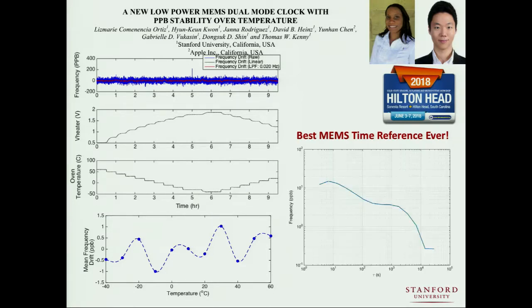It's very repeatable. If you make an Allan deviation out of the data on the upper left, there's details here that have to do with what's going on in the environment. I think the bump at about 1,000 seconds corresponds to the half-hour step intervals in our temperature profile. But the main thing about this curve, and what you like to see if you like Allan deviation curves, is you like them to keep going down as you go to the right.